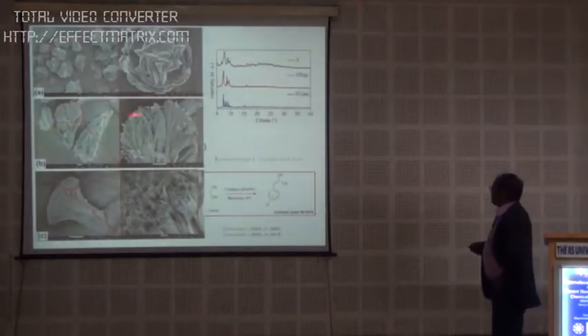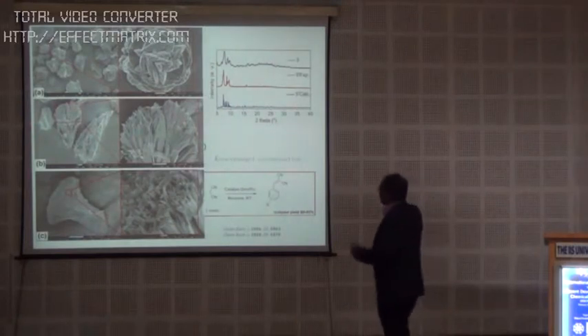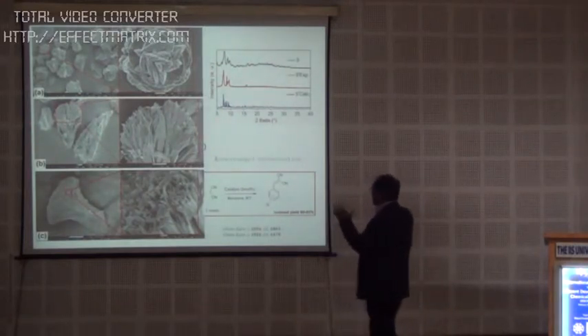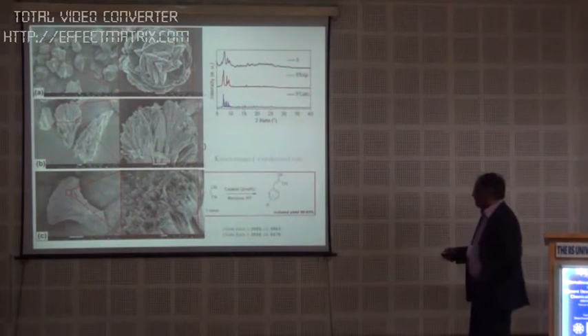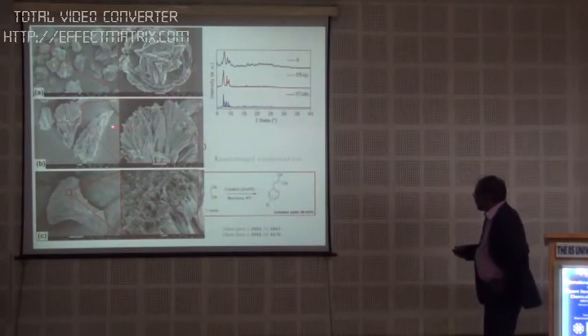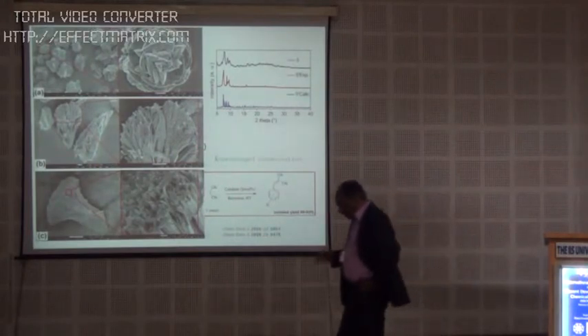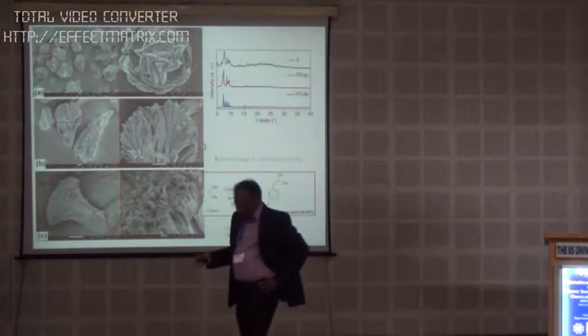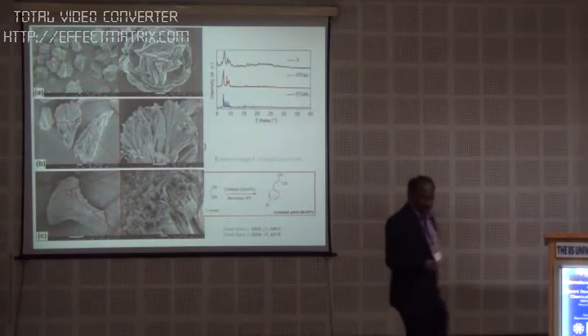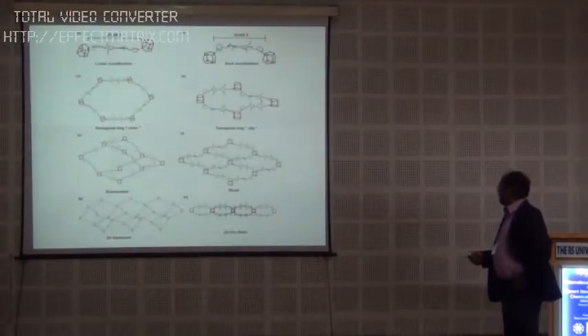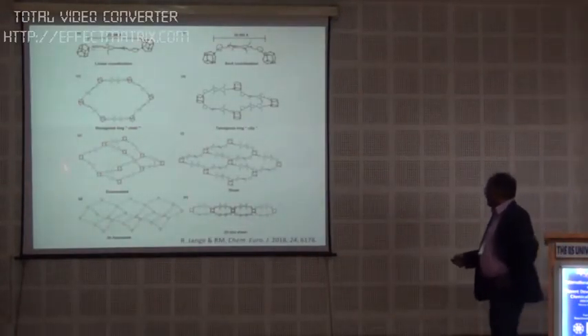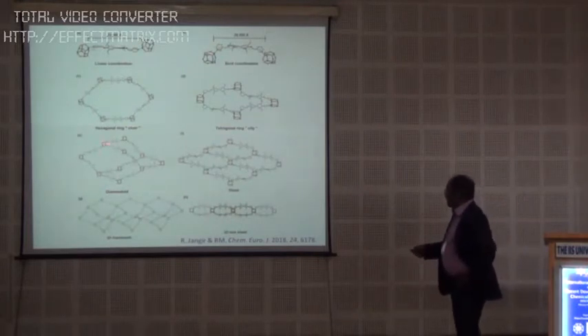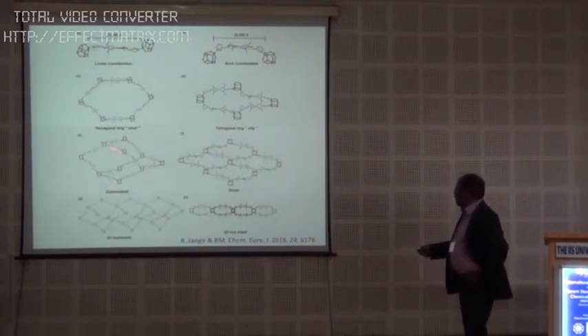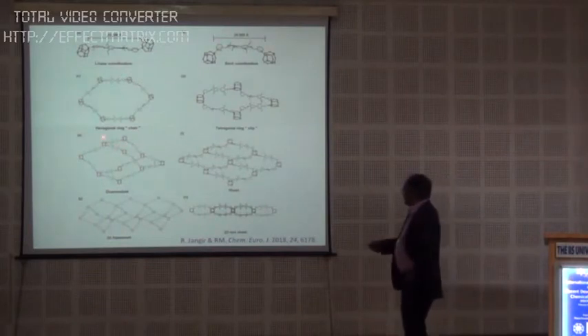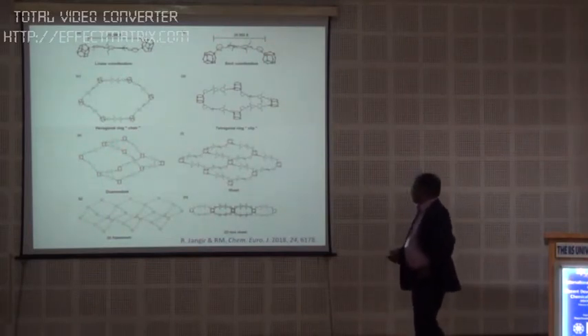What is important here is that these are microcrystalline. These nicely come as something like a broccoli or a cauliflower kind of structure. And if you pluck one of these small single crystals, which is only about 10 microns by 10 microns by 50 microns, and if you have a good X-ray beam, you can even get a structure. That's what we did, and it showed that these do really have a diamondoid network. And as I said, these walls are both hydrophobic because of the isopropyl group, as well as functional because of the imine groups that are loaded.